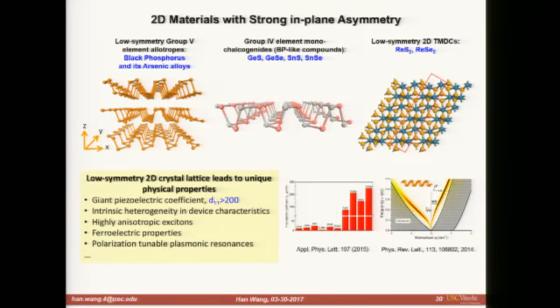Also, their low crystal symmetry gives these materials some very unique properties, like the giant piezoelectric coefficient over 200 predicted theoretically for single-layer tin selenide, and also polarization tunable plasmonic resonances in black phosphorus. Also, some ferroelectric properties are starting to be studied theoretically recently.